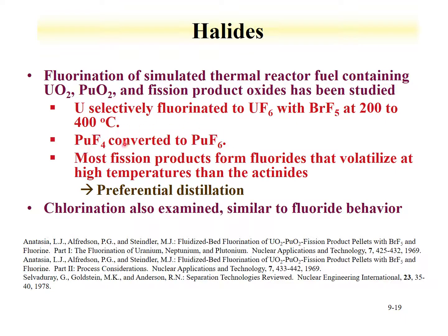The plutonium can also be volatilized as the hexafluoride. Most fission products that form fluorides volatilize at higher temperatures than the uranium or plutonium, so one can have a preferential distillation for the purification of the actinides from the fission products.